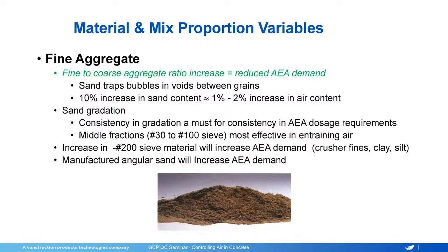Now, you can use the FM of your sand as a tool to track consistency of the material, but you can't just look at that alone. You're going to have to look at each sieve size and make sure that it's being consistent. And what you will likely find is that you need a much tighter range of control than what ASTM allows. So, for instance, one sieve in ASTM has a 10 to 30 range. That's a huge range. So if you're at 10, you're going to struggle to get there. If you're at 30, and this is the 50 sieve, then you're going to have no issue getting air.